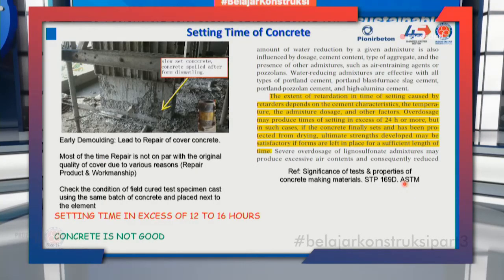Then one last thing is the setting time of concrete. The general opinion I find is, setting time in excess of 12 to 16 hours means the concrete is not good. It's very bad concrete. It's a totally wrong concept. You look at here, your ASTM standard says, setting time in excess of 24 hours. Even if there is a long setting time of 24 hours, it will not affect the final strength of the concrete provided you properly remove your formwork.